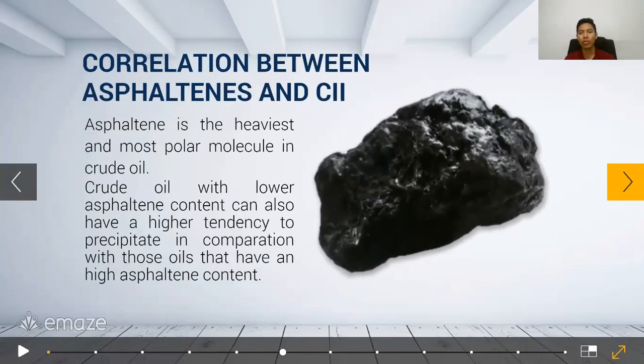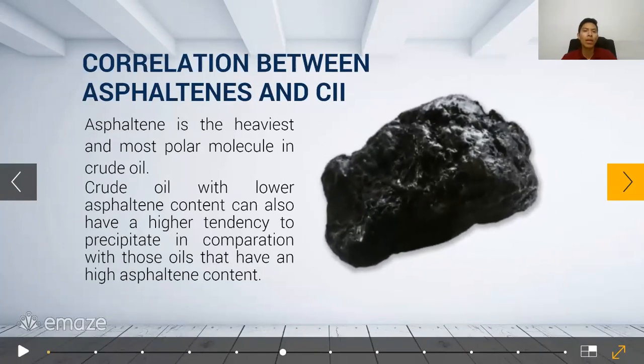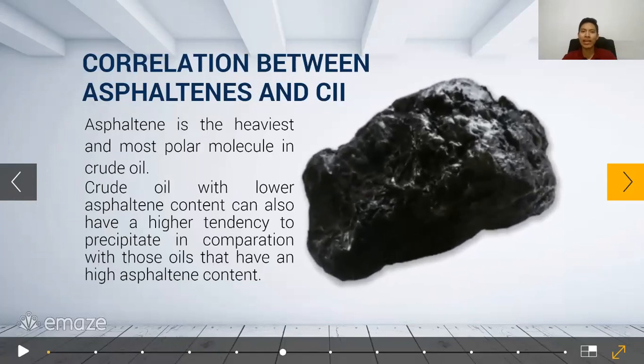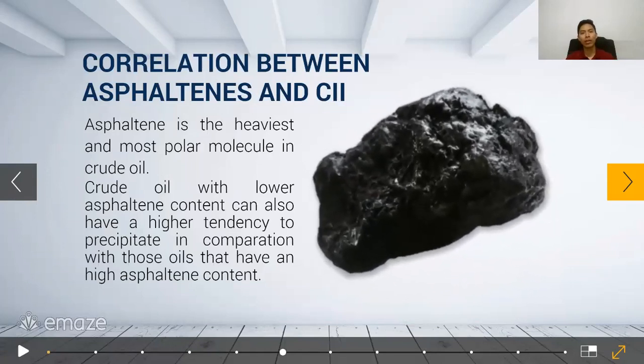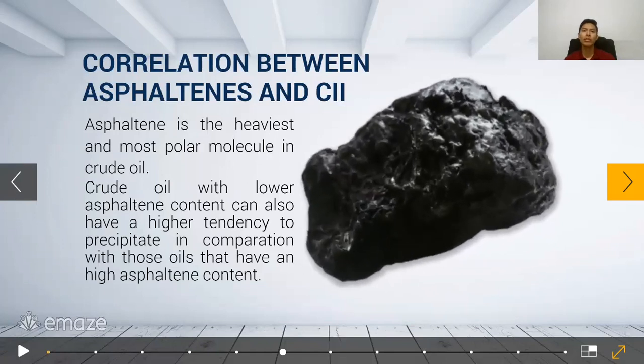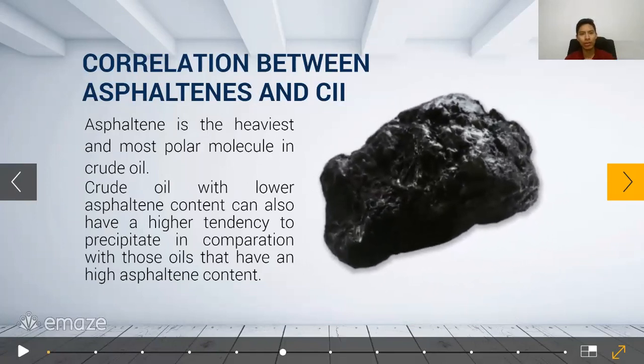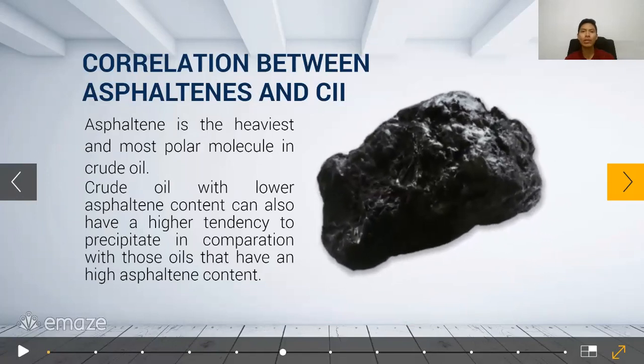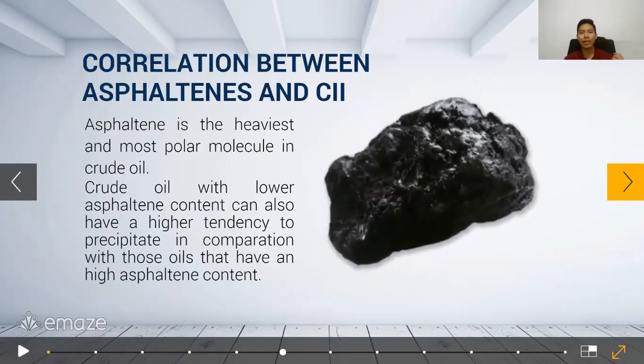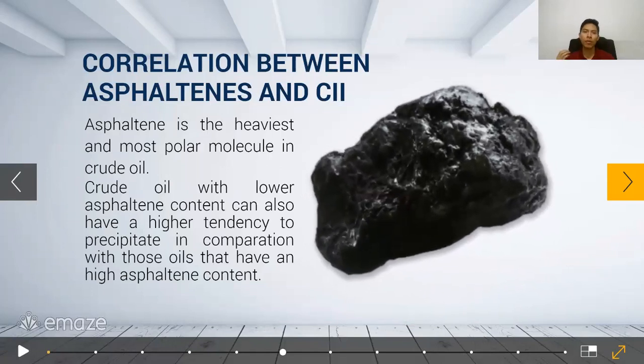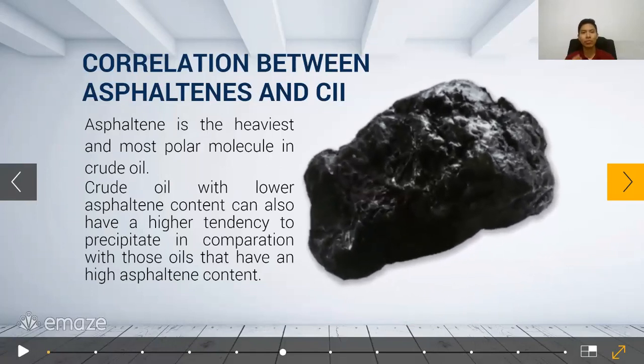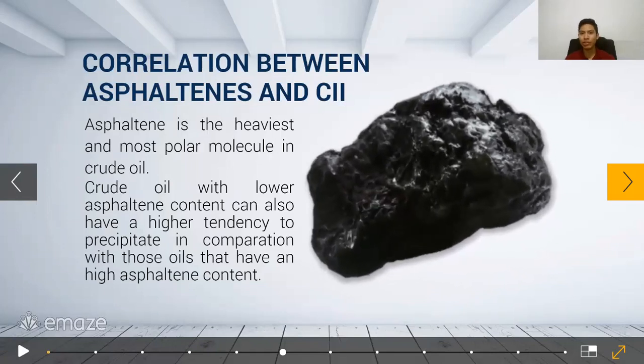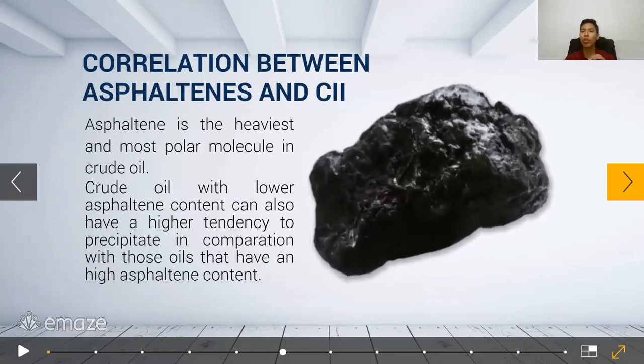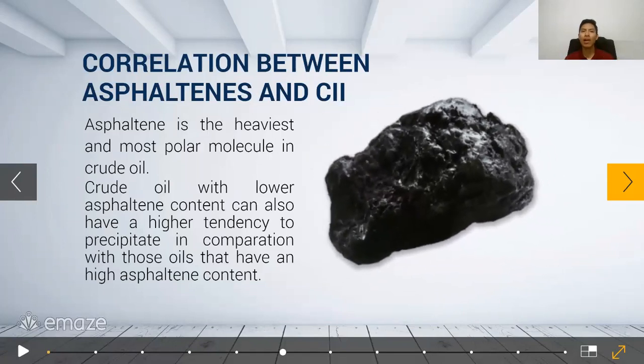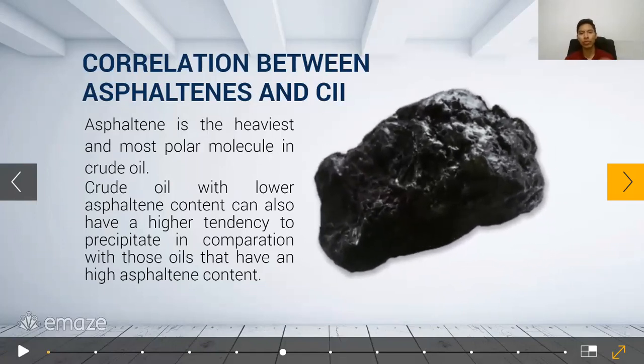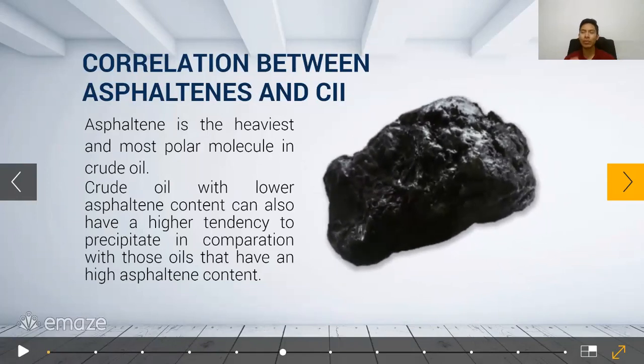Correlation between asphaltene and the colloidal instability index. The asphaltene is the heaviest and most polar molecule in the crude oil. Even though sweet crude oil contains low asphaltene, this doesn't mean that it has a lower tendency to precipitate than crude oil that has a high percent of asphaltene, because several researchers have shown that crude oil with lower asphaltene content can also have a higher tendency to precipitate in comparison with those oils that have a high asphaltene content.